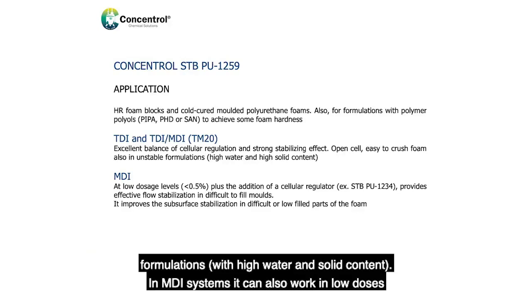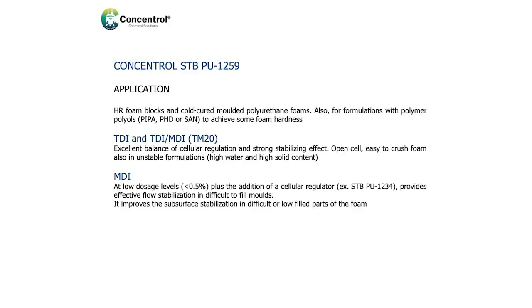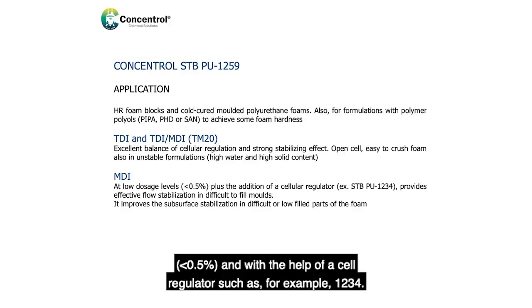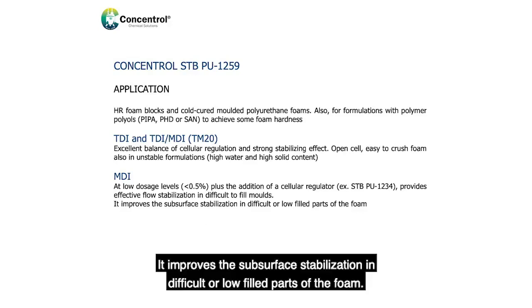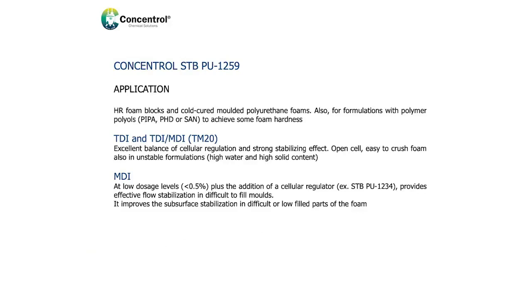In MDI systems, it can also work in low doses, less than 0.5%, and with the help of a cell regulator such as, for example, 1234, it improves the subsurface stabilization in difficult or low-filled parts of the foam.